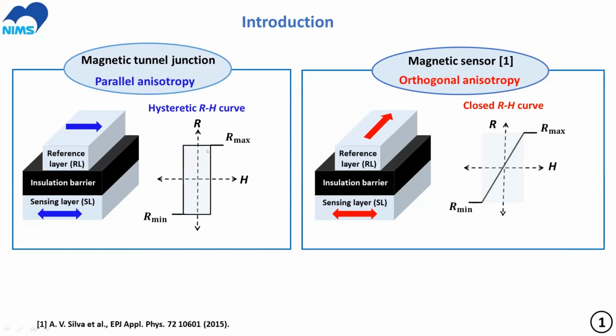The point in this case is that the transformation between these two resistance states, or these two magnetic states, happens abruptly, switching suddenly like this. So considering the positive and negative sweep, you will get a squared hysteresis loop. And in this conventional magnetic tunnel junction, you can't use this conventional MTJ as a magnetic sensor.